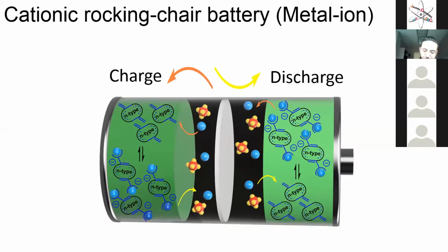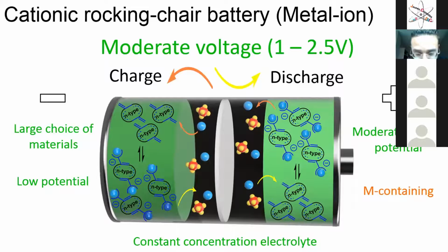So this battery configuration can provide moderate voltage, I would say from 1 to 2.5. This is what we can do currently, but we are hoping for the better, to increase it to 3 volt if we can. And at the anode level, we have a large choice of the materials that can react at low potential. I'm going to show you some examples of this. And then at the cathode side, we have some cathode materials that can be used for this configuration, and they can provide moderate to high potential. And here you can use a conventional electrolyte. You don't need to work on the electrolyte, but the challenge here remains at the cathode, because we need to find some metal containing cathode materials that are high voltage and air stable.